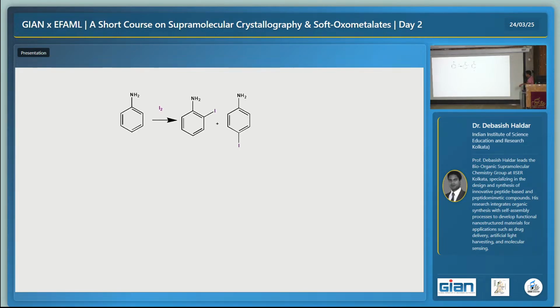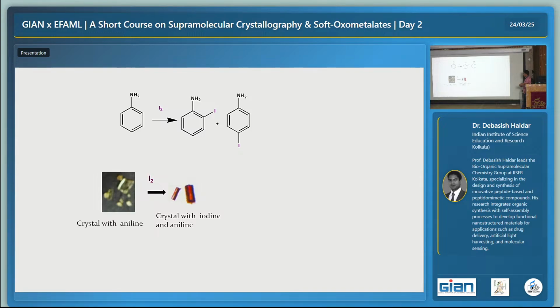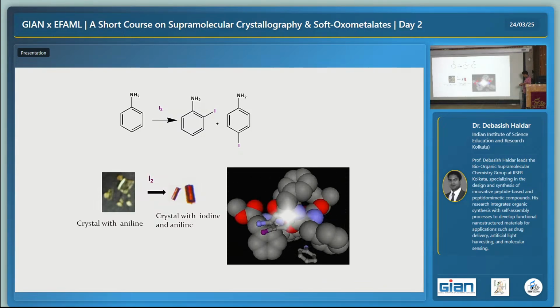And now the question is whether this is ortho-iodo or para-iodo, so which form, if there is any selectivity. After exposure to iodine, the crystals are very, very bad in shape, as a huge amount of iodine just absorbed over the crystal, but we were able to take data. The data is not very good, but we figured out that the ortho-iodination is taking place. This is because of the particular position of this compound inside the channel.